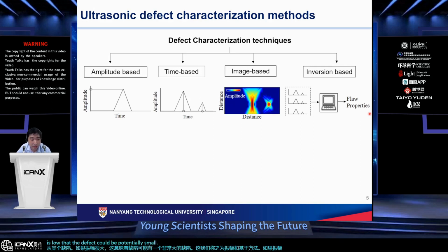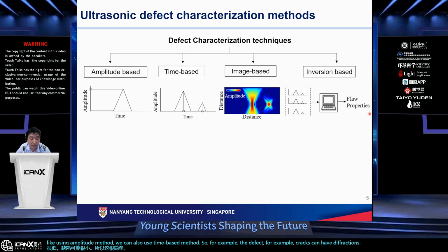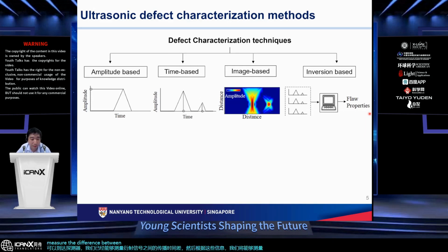So that's pretty straightforward, like using the amplitude method. We can also use a time-based method. For example, defects such as cracks can produce diffractions, and these diffracted signals arrive at the detectors, and we can measure the travel time difference between the diffracted signals. From this information, we can measure the difference between different tip diffractions, and hence know how severe or how long the defect is. So we call it a time-based technique, right? This is often used in weld inspection. We call it the time of flight diffraction method, TOFD.